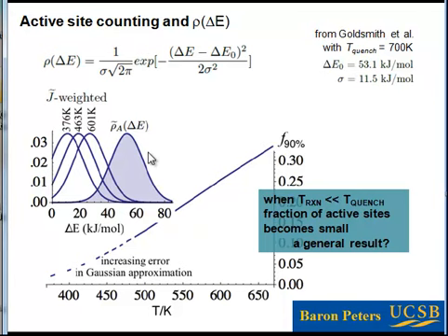Once you calcined that catalyst, you made a catalyst at 700 Kelvin in this example. That's where we got these numbers. You made this catalyst at 700 Kelvin, and its sites are what they are permanently. Now you lower the temperature, the wings of the distribution are still there, and at lower and lower temperatures, they become more and more heavily contributing to the average rate.